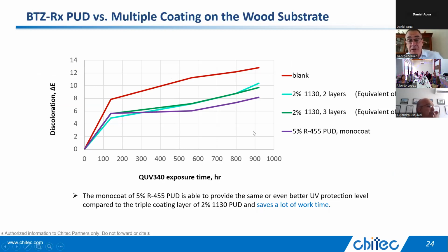And here, this is the QUV exposure. It shows how good this polyurethane dispersion with 5% polymerized in is. And that's comparing it to ones where we put on multiple layers with 1130. In this case, it comes out to the equivalent of 6% UVA. And we're still better with only 5% of the R455. And that's presumably because of the loss, the migration of the 1130. And if this was done with a car wash soap test or a rain test, I think we'd see a much bigger difference. We'd see that the 1130 goes away even quicker.